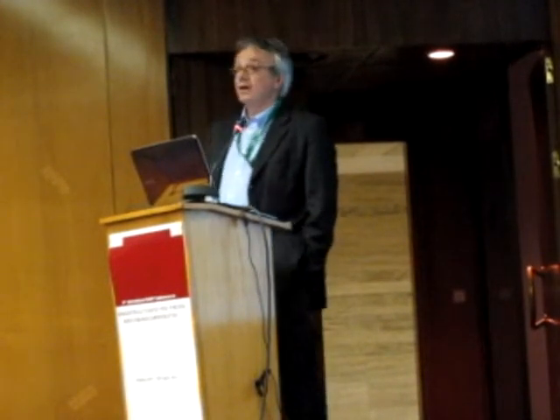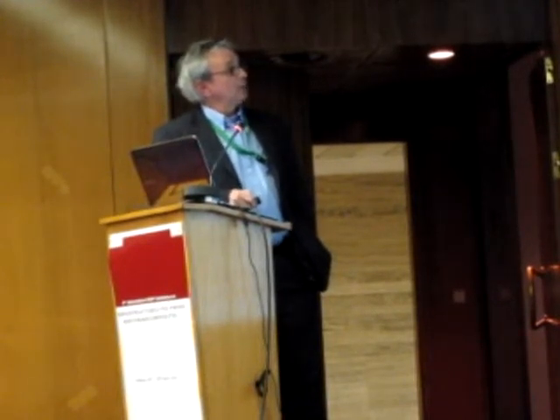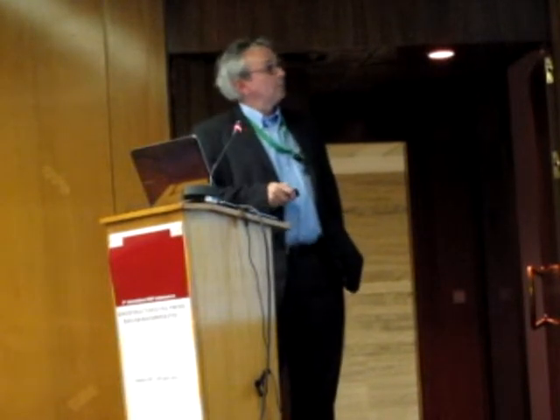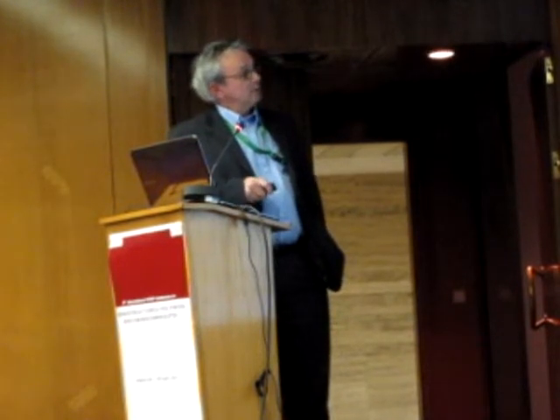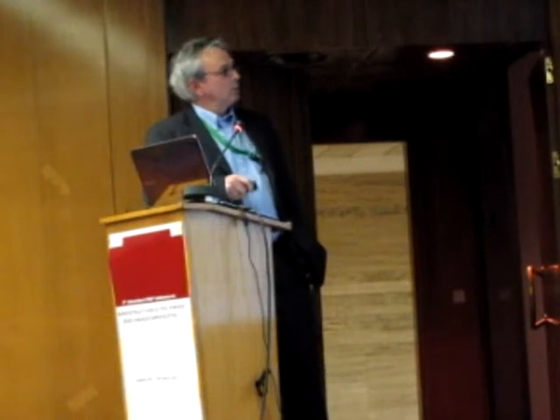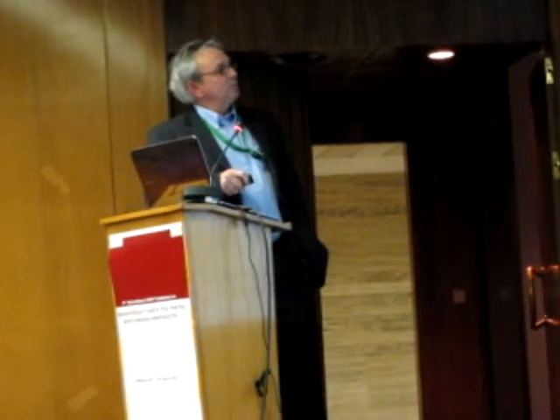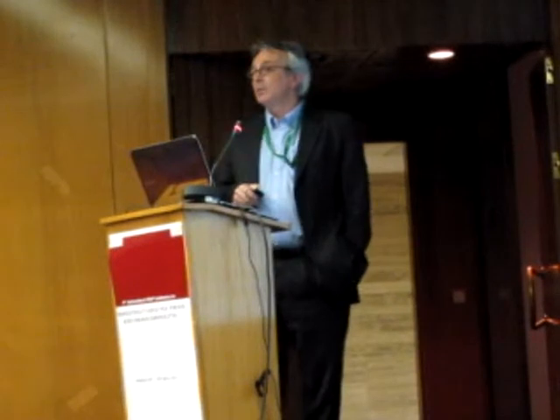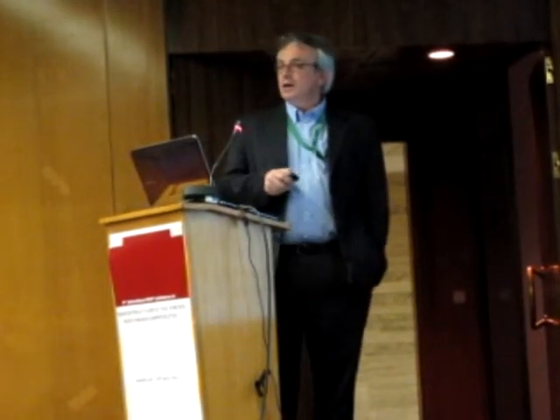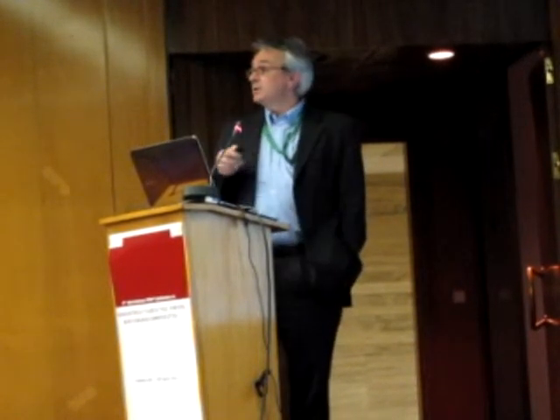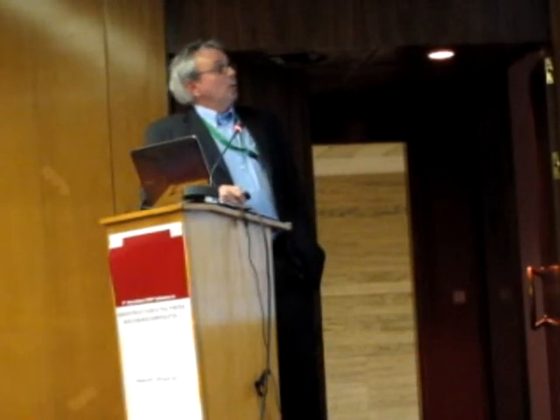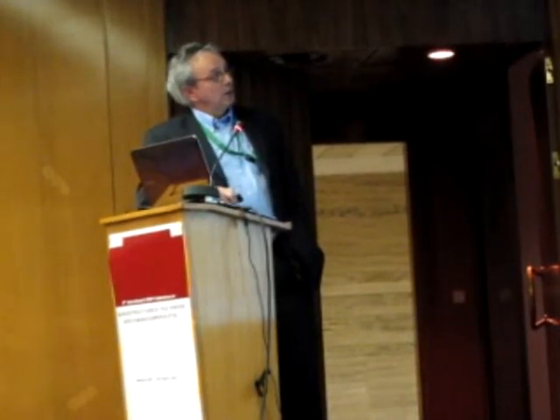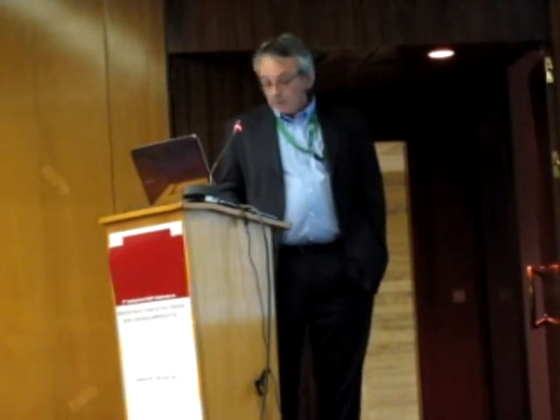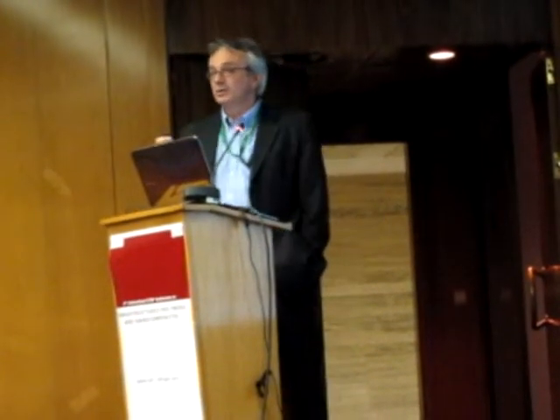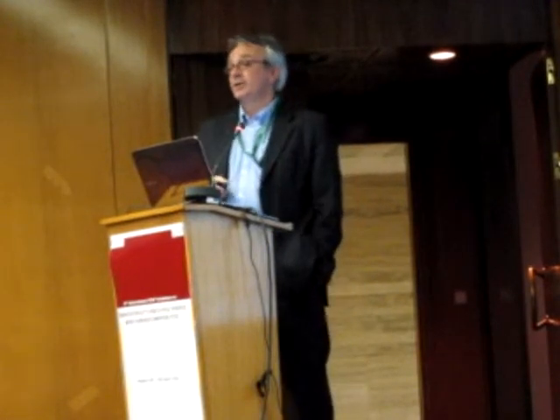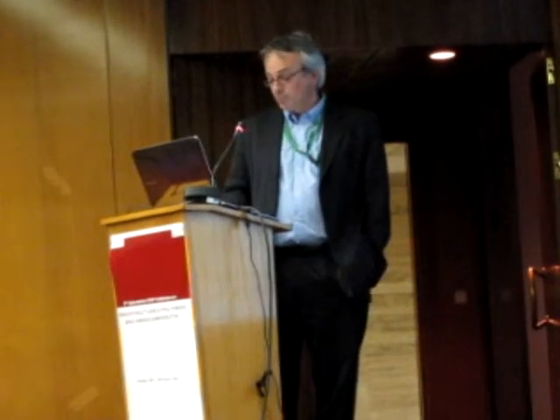Now we put the lactide with silica. That's the same G prime and G double prime for a given reaction temperature, which is above the crystallization temperature. So G double prime, G prime for the pure lactide: again, the increase of the shear modulus and the loss modulus. If you look at the lactide plus 5% of silica, you can see that now G prime is above G double prime even from the beginning, which means that the suspension of fumed silica in lactide is already a gel. So you polymerize the lactide into a gel structure, which you can retrieve at the end of the reaction, looking at the rheological behavior of the nanocomposites. That's one of the problems of processing of those systems, because if you put fumed silica, even 5% of a low specific surface silica, you already have a gel, which is sometimes a problem to process.